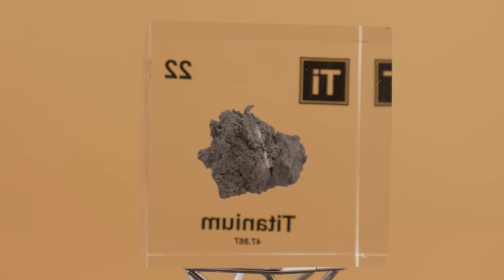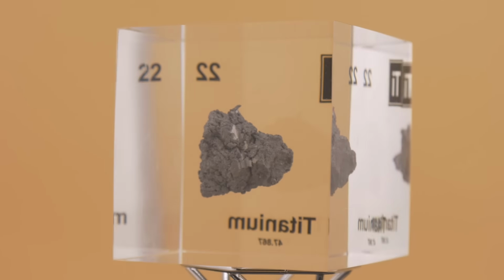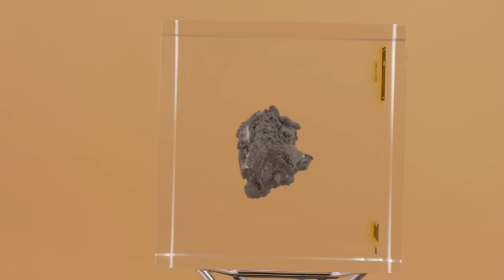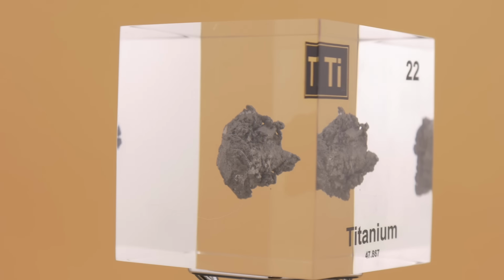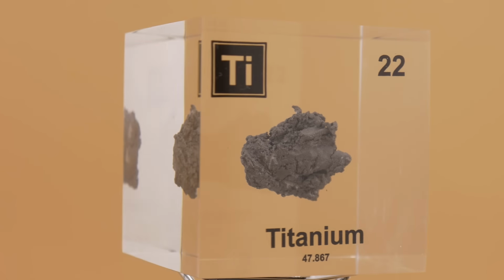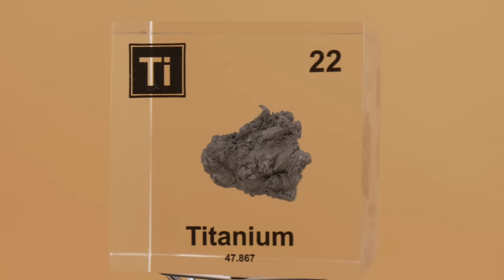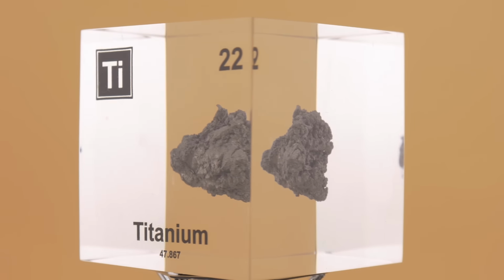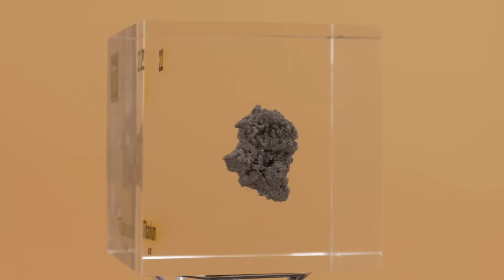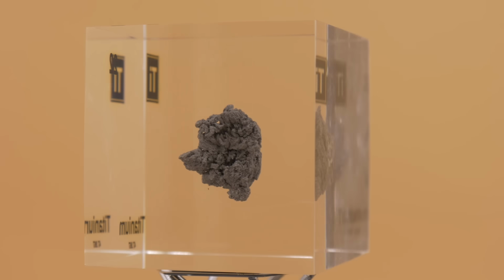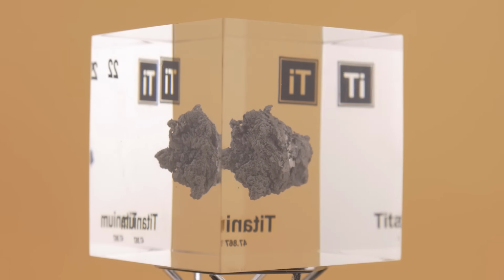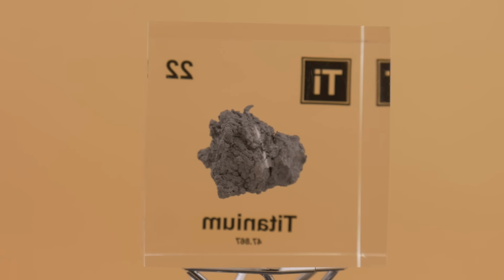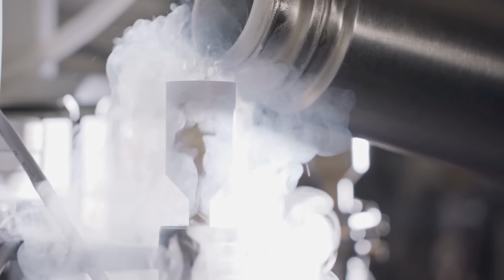This is one reason why welding or machining titanium requires special caution. Fine titanium shavings or powder can ignite like flash powder if you're not careful. When titanium burns, it reacts with oxygen, forming titanium dioxide, or with nitrogen, forming titanium nitride. Fun fact, titanium is one of the few elements that can burn in pure nitrogen gas. Normally we think of nitrogen as quite inert.